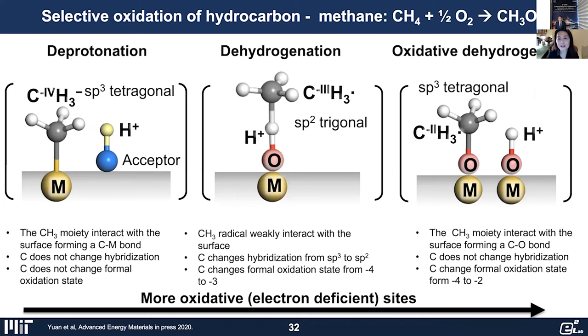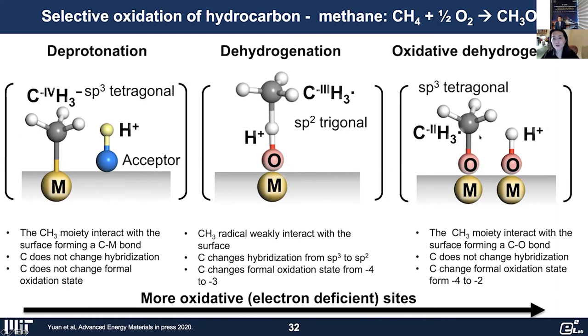This same idea can be extended to selective oxidation of hydrocarbons—for example, converting propane to propene or methane to methanol. One common mechanism is oxidative dehydrogenation, where you grab oxygen from the metal oxide if the oxygen has low vacancy formation energy penalty and is highly basic, grabbing hydrogen from hydrocarbons to form a proton. This is essentially the same mechanism one can leverage for selective oxidative reactions.